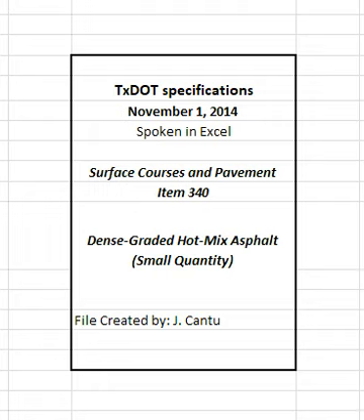Produce WMA within the target discharge temperature range of 215 degrees Fahrenheit and 275 degrees Fahrenheit when WMA is required. Take corrective action any time the discharge temperature of the WMA exceeds the target discharge range. The engineer may suspend production operations if the contractor's corrective action is not successful at controlling the production temperature within the target discharge range. Note that when WMA is produced, it may be necessary to adjust burners to ensure complete combustion such that no burner fuel residue remains in the mixture.